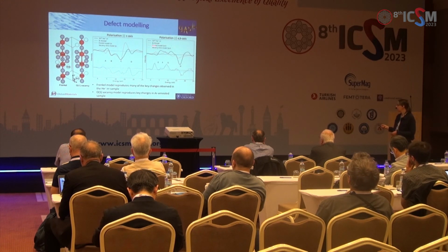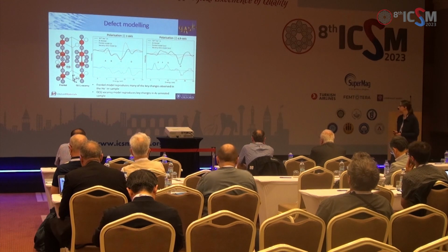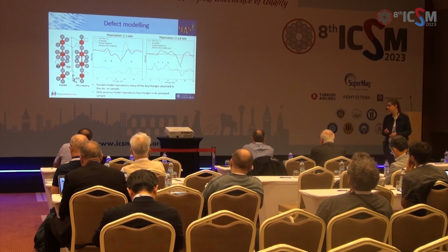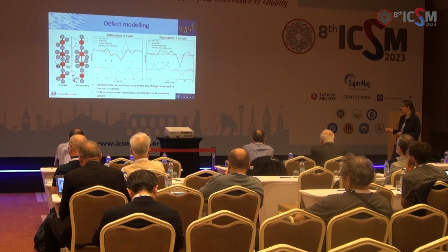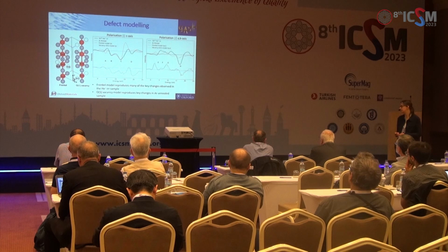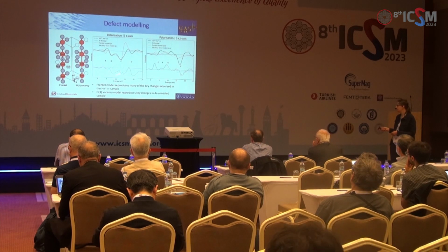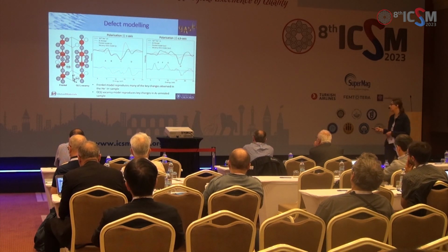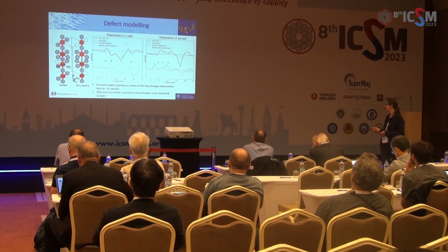This one and the other orientation is less clear, so maybe something else is going on as well. If we look at the argon annealed data, the black line is the experimental data for the comparison between argon annealed and pristine samples, and the blue is the O1 vacancy model. Again, we see roughly the same peaks and troughs in the same place in the model and the experiment. And in particular, we get a very nice match in this direction.